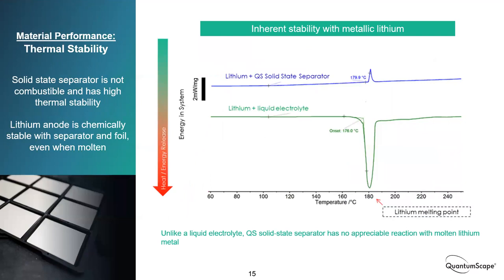I think the last data slide that I wanted to show is this one. I think it refers to the safety point. This is a material level test. What we're doing here is measuring the heat that is either generated or absorbed due to reaction between different components. I can explain this one at a time. If you look at the green curve, we've taken metallic lithium and put it in contact with a standard liquid electrolyte. And what we do is we increase the temperature looking for signs of reaction.